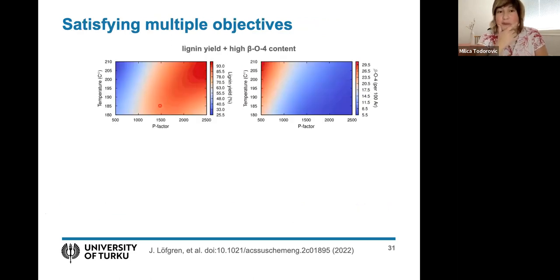So from each experiment, from each sample, we obtained not only yield information, but of course the chemistry of the lignin we were making. So here on the left, you see the surrogate model for lignin yield. And here on the right is the amount of beta-O4 functional groups in this lignin, which marks a particular chemistry. And you can see these landscapes look completely different. It's in the same search space, but the landscapes are quite different. So the first thing the experimentalist had asked us is, can we obtain both high lignin yield and high beta O4 content? And of course, this is very difficult because the high yield is in the top right and the high beta O4 content is the top left. So how do you reconcile these two?